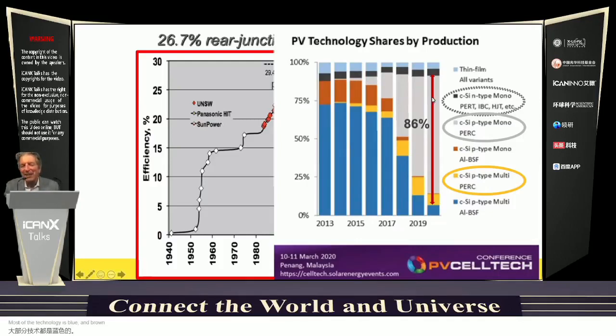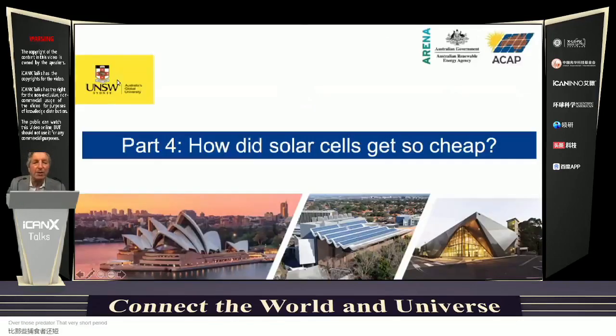So by 2020, the yellow and grey regions, a bit of the black is also PERC type technology, was accounting for 86% of production. So completely dominating the industry. So a very rapid transformation in the industry over that very short period. And I'll show some of the things that have happened as a result of that.